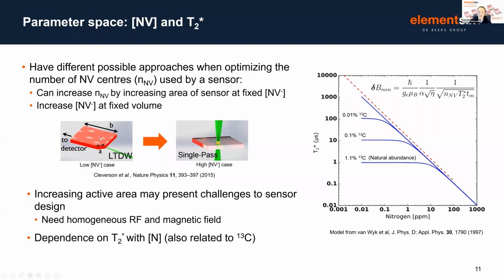Now, this only works in the case where we have a low concentration of NV minus, because in the high concentration case, the NV itself will start to absorb the laser that we're using to excite the luminescence. So if instead we think about a high NV containing sample, it's more typical just to focus a laser or an LED in a small volume of that sample in what's referred to just simply as a single pass arrangement.